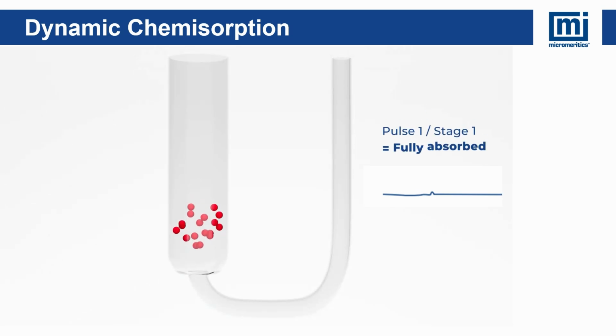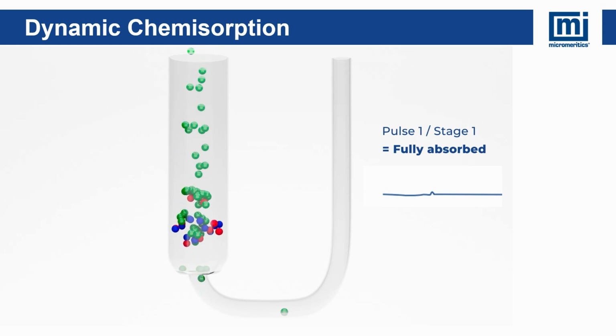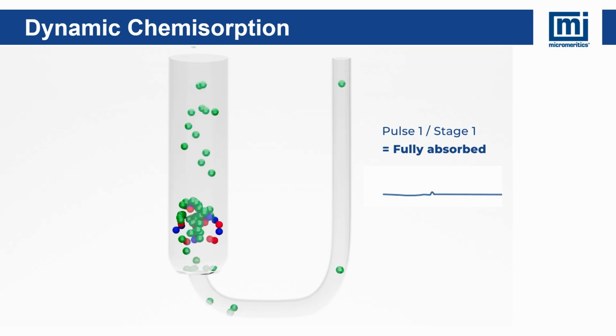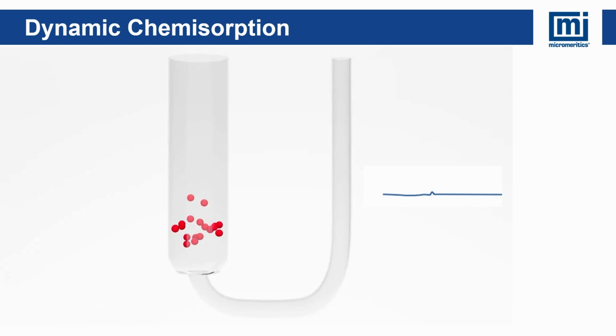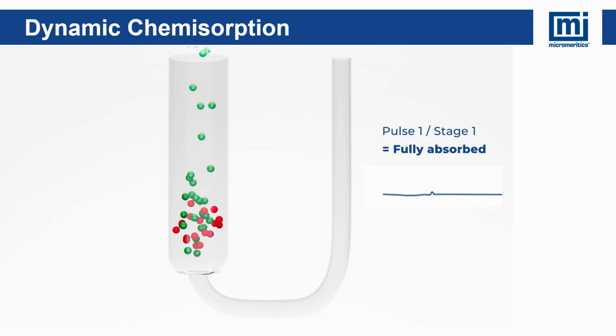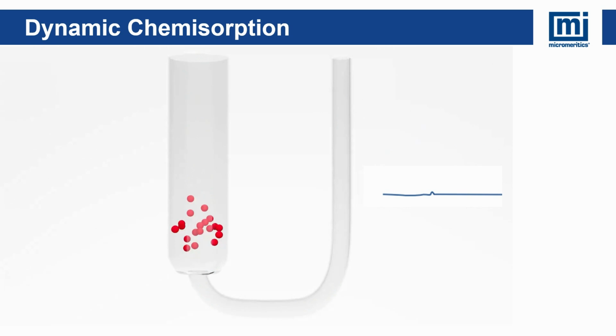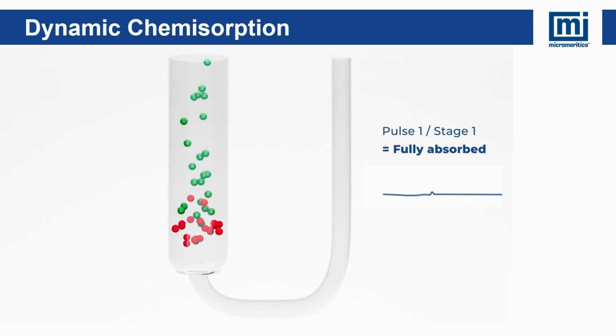The following animation illustrates what happens inside the test tube. The green dots represent the probe gas molecules. The red dots represent the exposed platinum crystallites, and the blue dots represent the probe gas bound to the surface of the platinum. In stage 1, most gas is adsorbed and a very small amount of gas passes through the detector. As you can see, a very small peak appears.